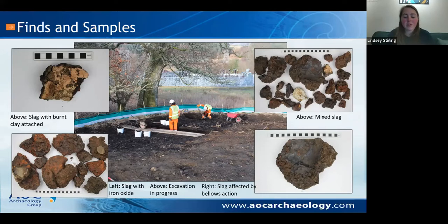So the finds recovered from the site were almost entirely iron slag, and also some occasional pieces of burnt clay from the furnace structures themselves. You can see the photos here show some of the recently washed pieces of slag that the team have been looking at. In the bottom left picture, we've got some patches of rust, which confirms that we're definitely dealing with iron-rich slag. So there was definitely significant iron working happening at the site.